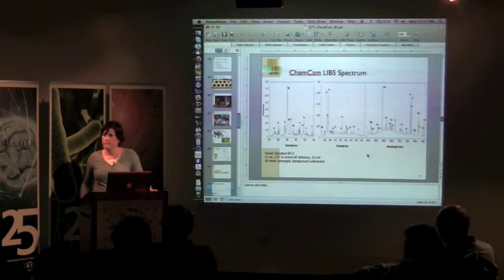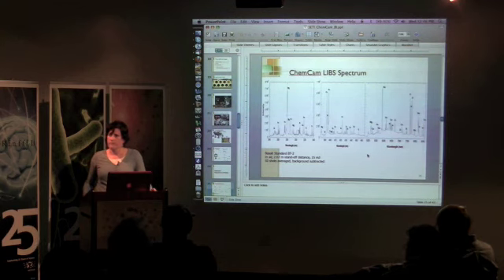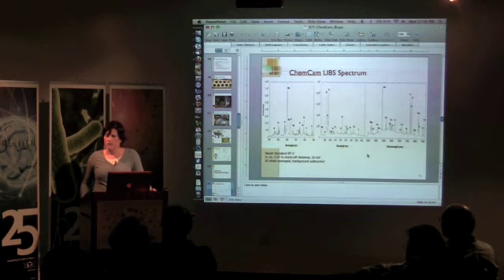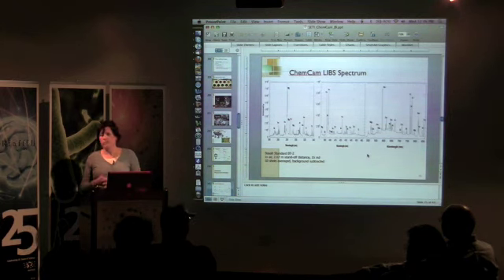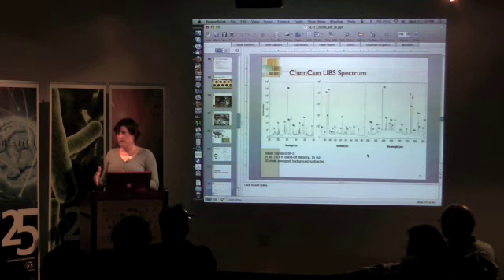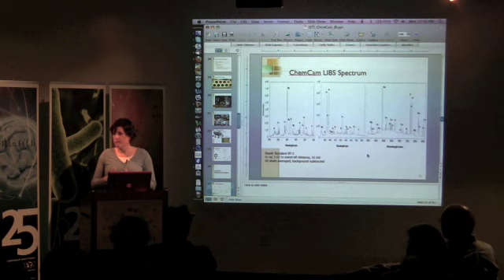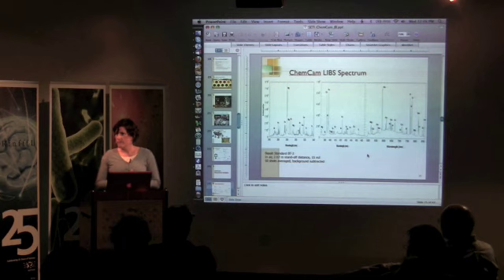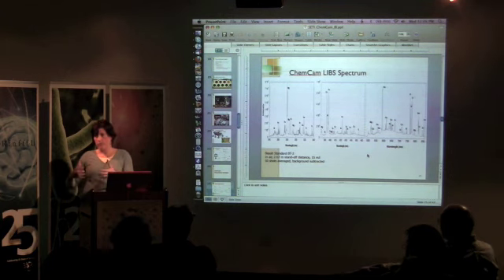And so presumably you've used carbonates as a target in your testing in the field as well. What sort of results have you been able to get by looking at carbonates? The ChemCam team so far has never taken ChemCam to the field. So there are other groups we work with who've taken a portable instrument of similar laser power to the field, and they have analyzed carbonates. But we're limited by just bringing materials from the field to the laboratory.